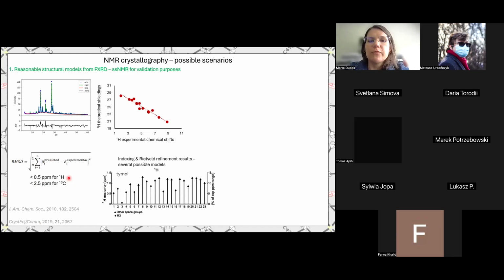It can also be used if we have several models from indexing and Rietveld refinement. It can sometimes happen, and this actually works. This is one of the first examples, by Lyndon Emsley, published in 2010, of thymol, for which they had several different models, and you can see that only one of them, this third model, gives an RMS error value below 0.5 ppm.